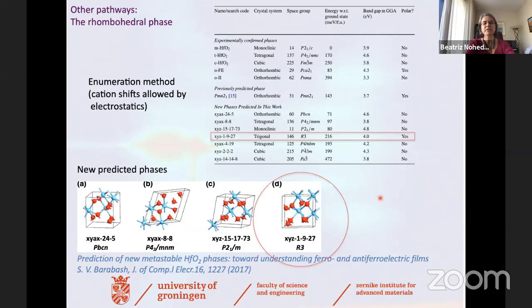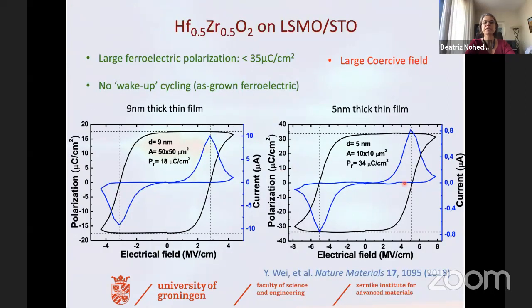And the very nice thing of this ferroelectric phase is that, first of all, it has a very large ferroelectric polarization, that can reach 34 microcoulombs per square centimeter. And at the same time, it doesn't need wake-up cycling. It's as-grown ferroelectric. It also has a relatively large coercive field, even larger than those films that are not epitaxial. And we wanted to understand why all this is.